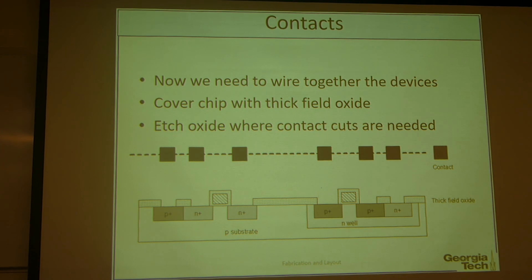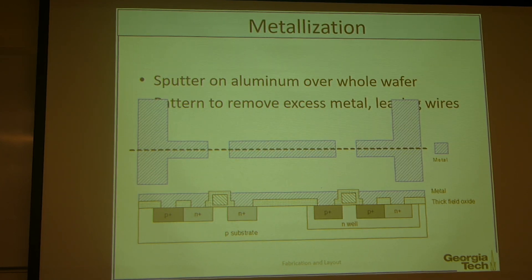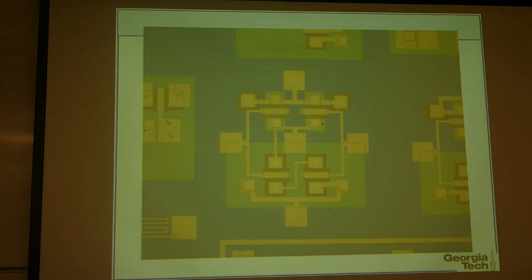For the beginning of the back end of line, we need to make holes for electrode connection. For the electrodes to be connected to the silicon surface, we first cover the chip with thick field oxide to isolate between the electrodes. We deposit the thick field oxide and then make holes. Then we deposit the metal using physical vapor deposition — sputtering is one kind of that. Then we pattern the metal and make the inverter. This is a finalized inverter photo from the microscope, showing the N-well at the bottom with P-MOS, and N-MOS on top.